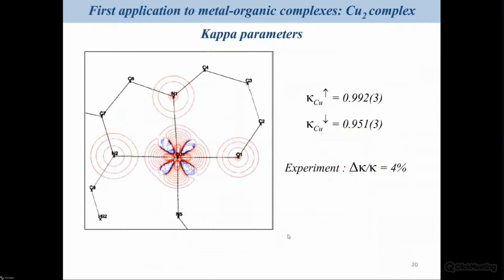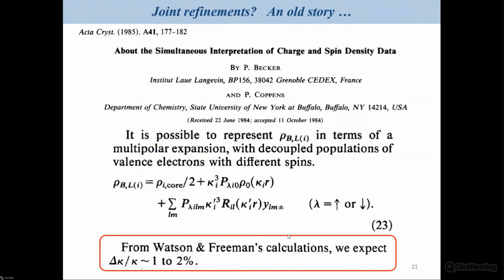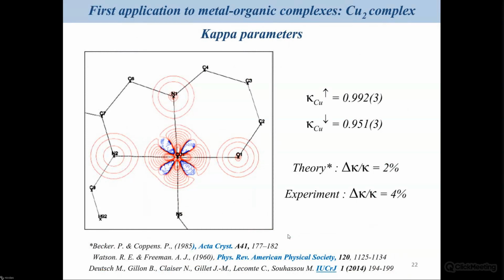So what we have been able to see also is that if you now look at the expansion of the spin up and the spin down density, you observe that the kappa values are different, and the difference is around 4%. And this is very interesting, because if you look back at what was predicted by Becker and Coppens, they imagined that it was possible to see such a difference, but in that case, they predicted only 1 or 2%. So anyway, it's very interesting to see that experimentally we have been able to confirm that it's possible to see the difference in the expansion of spin down and spin up.